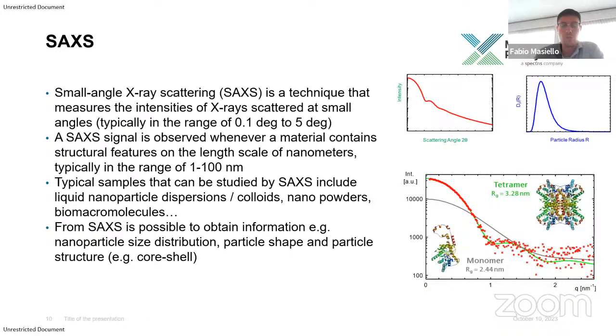So now we go to an even smaller length scale, in the range of 1 to 100 nanometers. As I mentioned before, the samples that can be studied by SAXS are much more broad. They include liquid nanoparticle dispersions, colloids, nanopowders, biomacromolecules, and more. From SAXS, what you obtain is the nanoparticle size distribution. For example, here you see a monodisperse sample with a certain particle radius, but also particle shape and particle structure. In this case, you see, for example, that with SAXS it's possible to differentiate whether this particular protein is in a tetramer or monomer configuration.